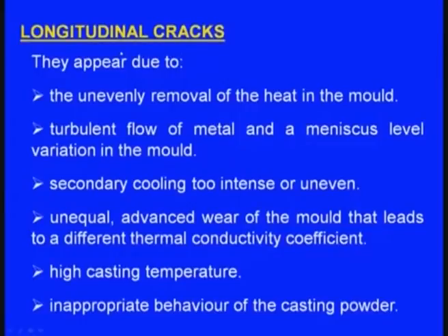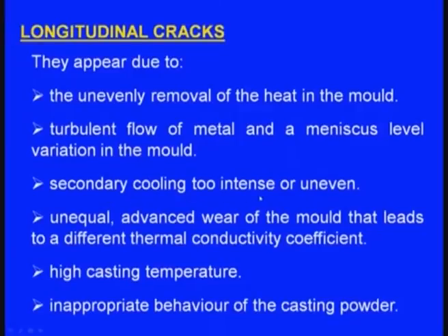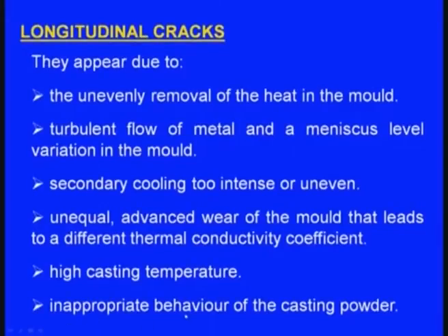Next defect is the longitudinal cracks. They appear due to the uneven removal of heat in the mold. They also appear due to turbulent flow of the metal and a meniscus level variation in the mold. They also appear due to secondary cooling that is too intense or uneven. They also appear due to unequal advanced wear of the mold that leads to a different thermal conductivity coefficient, and due to high casting temperature. Finally, they also appear due to inappropriate behavior of the casting powder. So, these are all the factors that are influencing the longitudinal cracks.